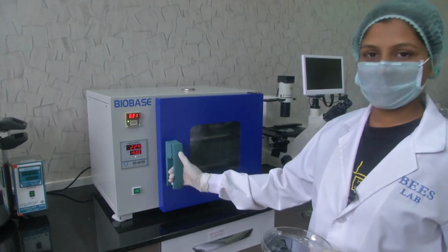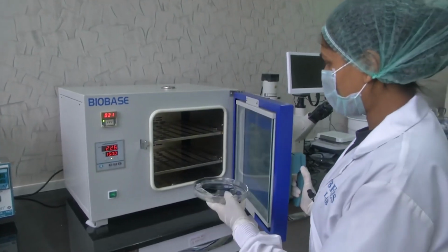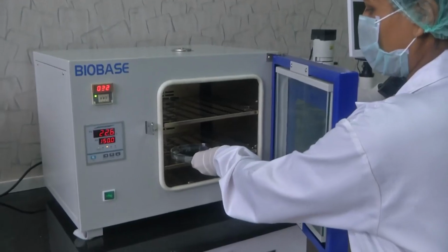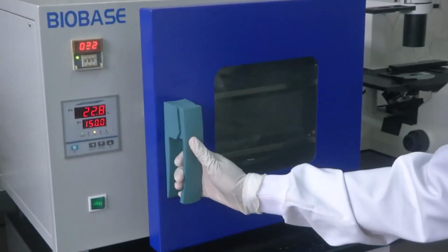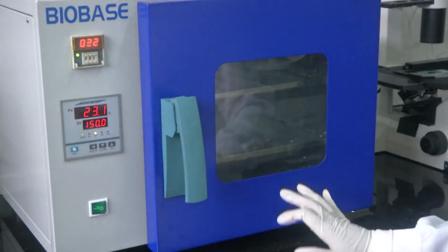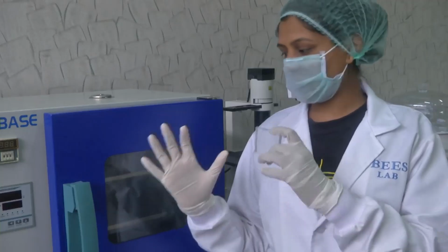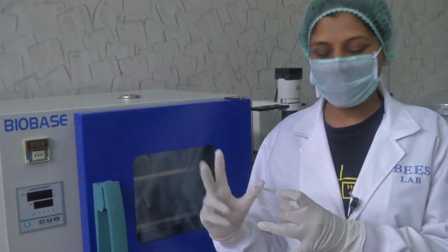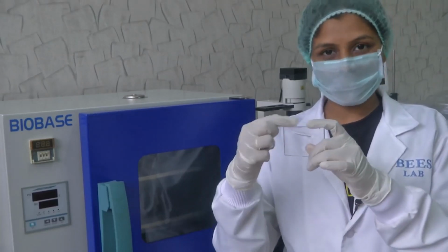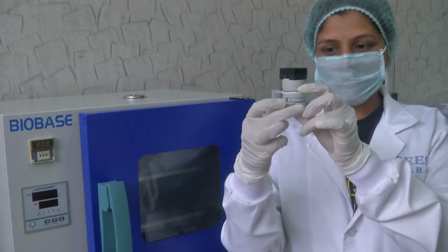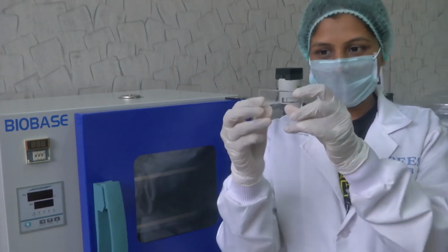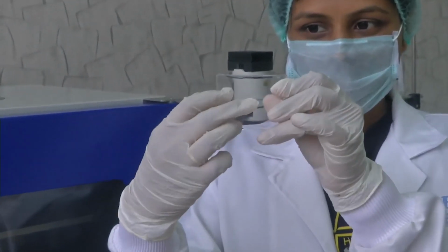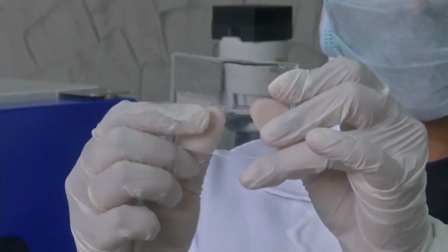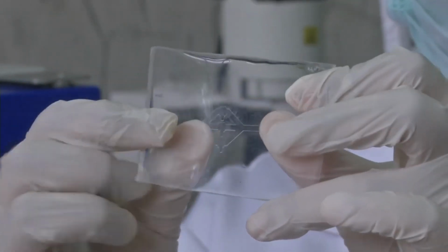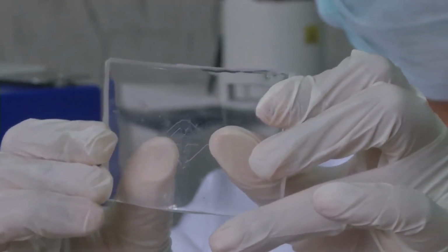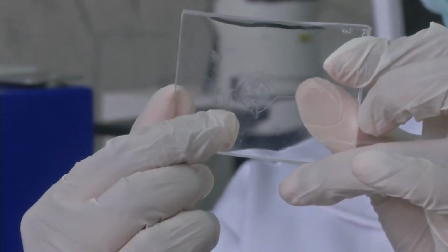It takes some time to increase the temperature. Now that we have the oven at 70, you can place your mold for 2 hours and leave it here at 70 degrees Celsius. After curing the mixture at 70 degrees Celsius for 2 hours, you get back your mold and then you could cut it using a surgical blade, and this is what you get. This is the flexible PDMS substrate on which this structure was embossed.